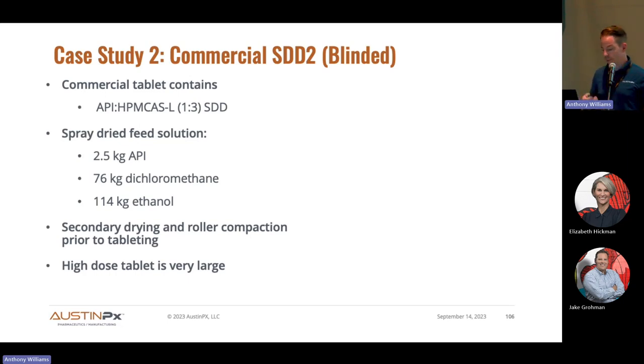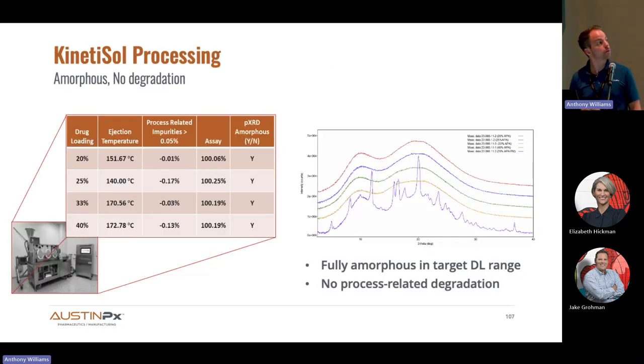And once again, a much more complicated downstream processing approach to achieve a tablet. So we were able to take this molecule and create a range of amorphous drug loads. So it works very well with KinetiSol. We were able to establish a range between 20 and 40% of single phase amorphous solid dispersions with absolutely no process degradation. In fact, we purified the API a little bit here as our process related impurities are negative.